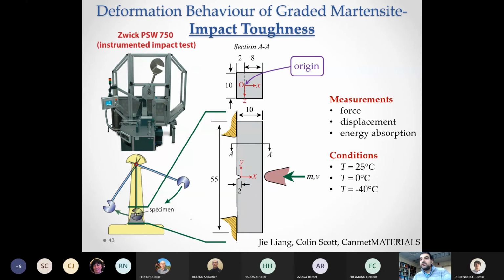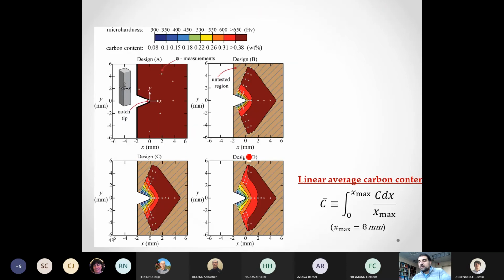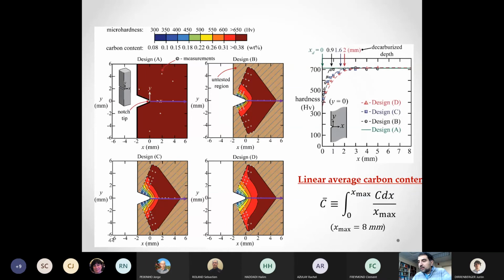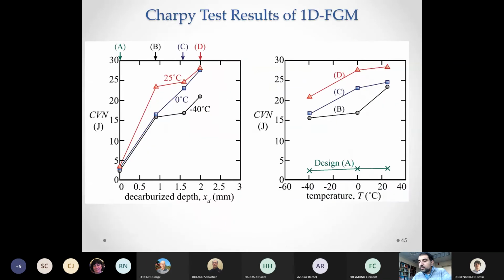And that leads me to the next point about fracture, where again we find that the graded material has a huge advantage compared to the traditional materials. So in this example, we did the so-called Charpy impact test to measure the impact energy. And the idea we had was to decarburize the sample here around the crack tip. So we decarburized for different times to get different carbon profiles around the crack tip. And in that way, we were able to measure the energy absorbed as a function of the testing temperature.